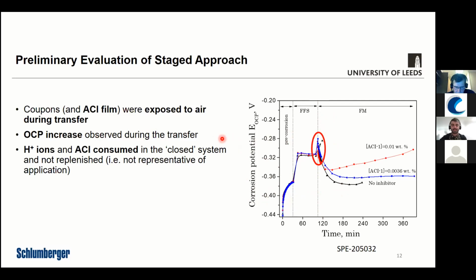And also fundamentally, even if there wasn't a transfer process, any experiment in this environment, particularly when you're using hydrochloric acid, which provides the corrosive species that would be consumed in any corrosion reactions at the surface of the carbon steel. Those species would be consumed during the experiment, so the strength of the acid and the potential for corrosion at the start of the experiment would be considerably different several hours down the line as the species are consumed and the chemistry within that environment changes.